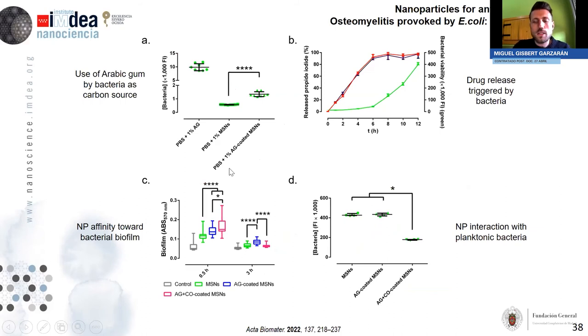And we carried out different experiments with bacteria. So first of all, we checked whether this Arabic gum could be employed as a carbon source by the bacteria. In other words, if bacteria could degrade this Arabic gum. And as we can see here, it is clear that it can, because only in the case where there was Arabic gum in the medium, there was an increment in the number of bacteria. Also, we could check that the bacteria could degrade this Arabic gum coating, because here we can see